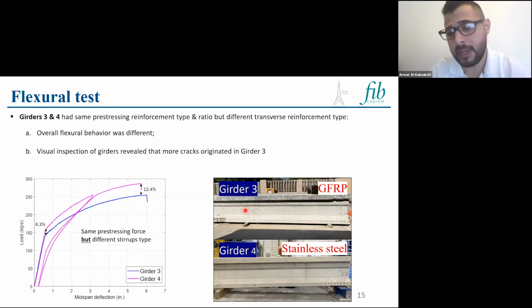And then after examining the girders after the test, we saw that many cracks originated in girder 3, and then we didn't see those cracks in girder 4. So the effect of using GFRP was that our load carrying capacity was reduced. Girder 4 had around 12.4% higher load carrying capacity.